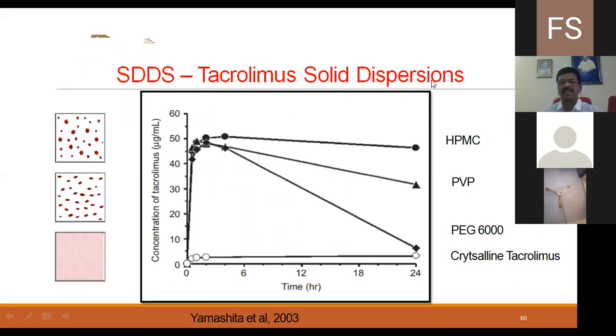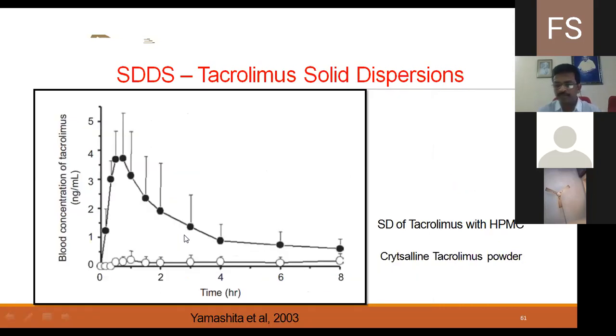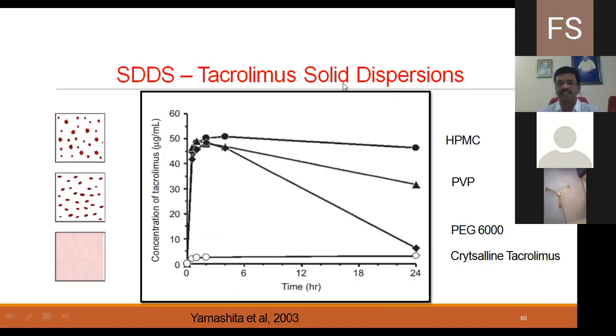When the tacrolimus solid dispersions were prepared and subjected to the study, we can see the spring effect. When it was taken in the crystalline form, we can see the line at the bottom of the graph, nearer to the x-axis. But when it is prepared in the solid dispersion form, the spring effect was seen immediately. That spring effect was seen in all three solid dispersions, prepared from HPMC, PVP and PEG 6000.